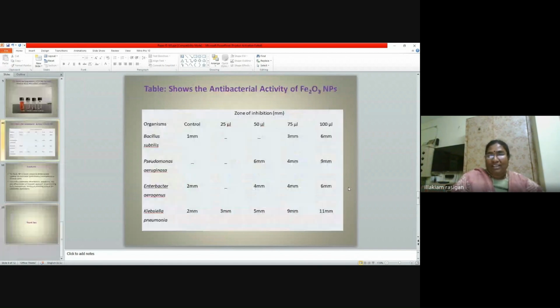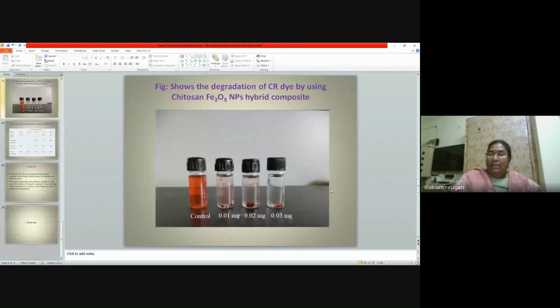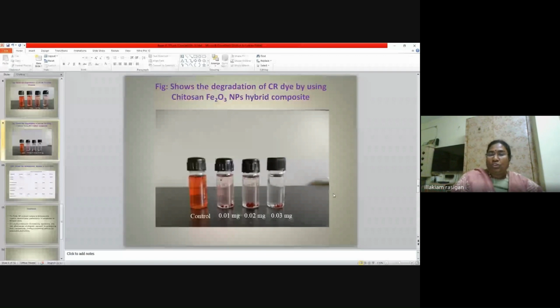Then afterwards, the same with the nanoparticle coated with the chitosan. This is chitosan alone. I have performed this experiment, and then I have performed the same experiment with chitosan-coated iron oxide hybrid composite. Compared to the chitosan, the nanoparticle combined with the chitosan degraded the dye very fast, and I have quantified with the same procedure. We have carried out qualitative and quantitative analysis.